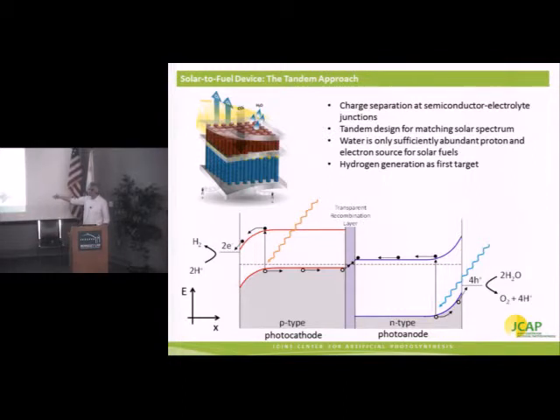So in this material, as you make an electrolyte interface between the semiconductor and the electrolyte, upwards band bending occurs. So you see these bands are bent upwards. This is a macroscopic electric field. So when we photoexcite carriers, so a photon is absorbed here, an electron is excited from the valence band to the conduction band, there's an electric field that drives those electrons, the majority carriers, away from that interface, and the minority carriers, which are holes, to the interface. These holes can then be transported to a catalyst and drive the water oxidation reaction, which generates our protons.